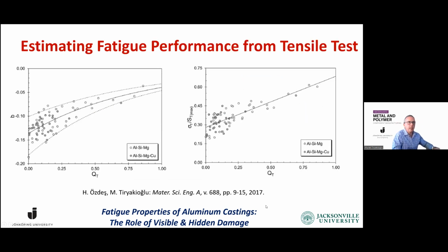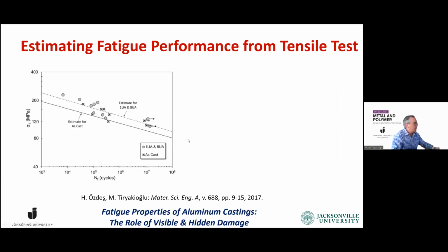We published this about 5 years ago. Here's the quality index, and here's B. And you can clearly see that, yes, there's a large scatter at the beginning, but the trend is very clear. And the strength coefficient of the Basquin equation is also changing linearly with the quality index or loss to damage. So with that, can we predict the entire SN curve? And the answer was yes, more or less.